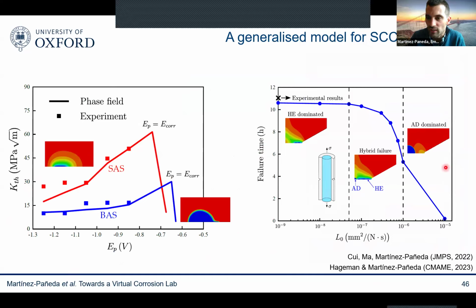And we use this model to understand also the classic experiments by Gruhl. These experiments were done in the 80s, and he was trying to understand whether aluminum alloys will fail due to corrosion or hydrogen embrittlement. So he did some very clever experiment where he exposed some cylindrical samples to a corrosive medium. He protected the outer surface, and he said if failure initiates from the inside, this means that it was due to corrosion. If it's near the notch, it's due to the hydrogen that is traveling through that towards the stress concentration area. And we saw that with the model, we are able to predict quite nicely their experiments.